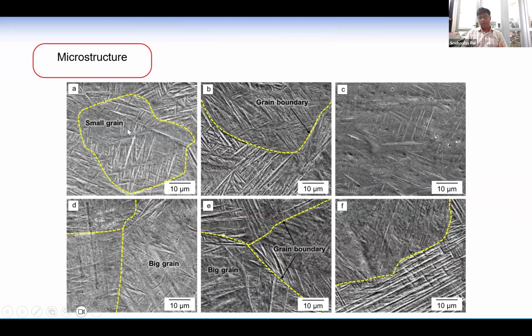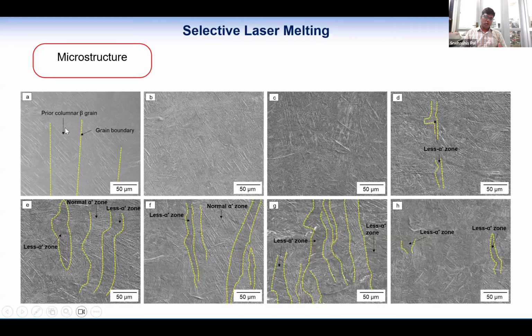So we can get small grain to bigger grain, or irregular grain to the classical hexagonal grain. The columnar grain can also be regulated, from thicker to thinner. You can also control the martensitic structure by changing the process parameters, mostly these three: laser power, scanning speed, and hatch spacing. Those are the three laser parameters.